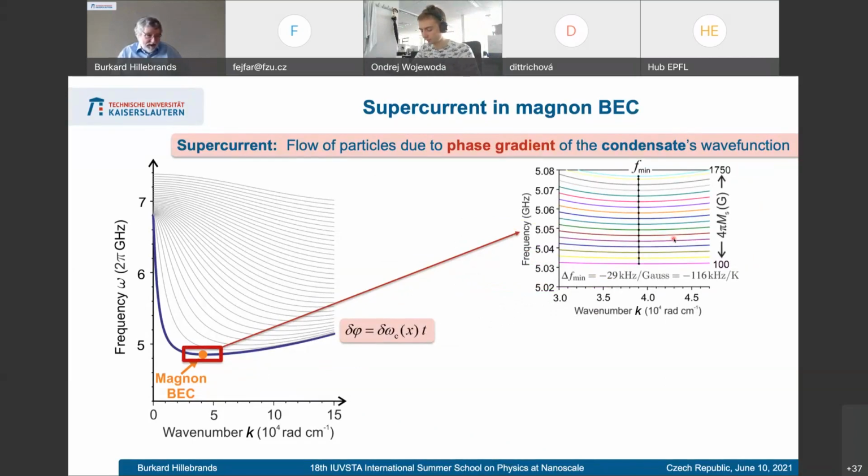And everything is easy in magnonics. That is always my key message I would like to convey, because we have so good control on the system. For instance, if we look at this dispersion curve and plot it as a function of temperature, we can do so because we know that the saturation magnetization is temperature dependent. So we can just change the temperature, and correspondingly we can change the saturation magnetization. And then you'll see that if we change the saturation magnetization between these two values, 1750, 100 Gauss in this